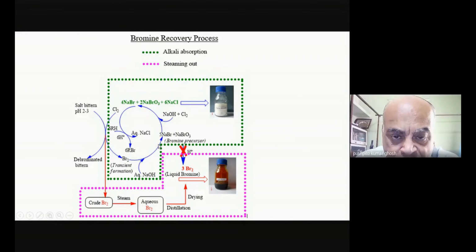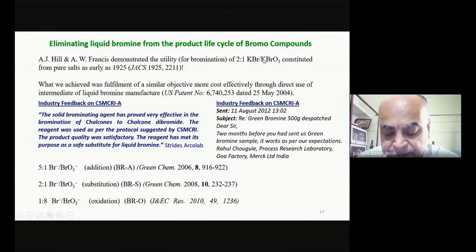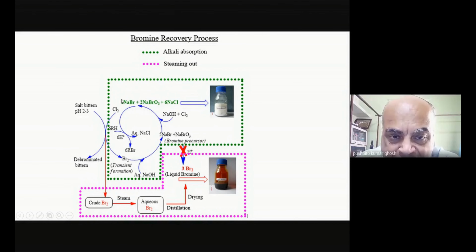In the cold process, what then is done is that this bromine is trapped in alkali. So here you can see NaOH, and you end up making 5 is to 1 sodium bromide to sodium bromate. If you reacidify this, you'll get bromine, and then you can distill that bromine and you'll get pure liquid bromine. That's the standard process. What we did is that we took this, we could either use this mixture or we continued oxidizing it further and converted it into this 2 is to 1 bromide to bromate, which is what Hill and Francis had done. What was the difference? Hill and Francis had taken pure KBr and pure KBrO3, and then they had mixed it. Obviously, it would be a much costlier product. Whereas here, we are getting the product itself in a mixed state.